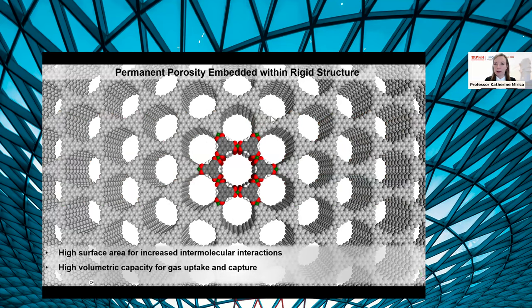Another really important benefit of these structures is the permanent porosity that is embedded within a rigid structure. So we have high surface area, which is great for increased intermolecular interactions when we're trying to do sensing. And we also have high volumetric capacity, which is important when we're trying to uptake and sense gases within these materials.